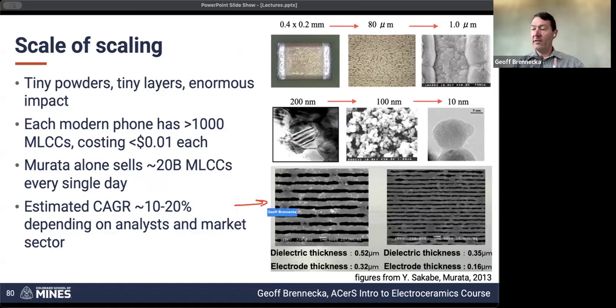So when we look at these, again, these are some old examples borrowed from Sakabe-san from Murata. You can see in cross section here, the dark areas are the electrode layers, and the bright areas are the dielectric. And you'll notice, for example, here's a region where the dielectric actually sort of oozes through. The electrode layer is discontinuous and has gaps in it. But remember, we're only looking at a two-dimensional slice, and so this electrode here, if we extend into and out of the page in some way, is still going to be connected to these other regions around. So it's going to be sort of like a Swiss cheese. It's got a hole in it. That hole is filled by the dielectric, but that's no big deal because as long as that's insulating, it's fine. We've lost a little bit of performance because of that, but it doesn't short circuit.